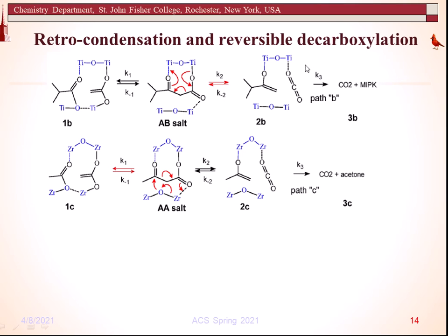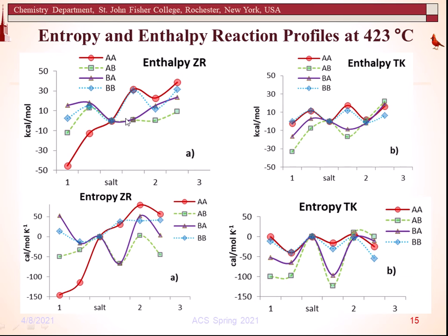We have tried to obtain the 5 rate constants shown on the scheme through regression analysis fitting the experimental data. So we have obtained activation parameters, which we try to use to find the thermodynamic values by the difference between the activation parameters for the forward and reverse reaction to build the energy profile for the enthalpy, entropy, and free energy.